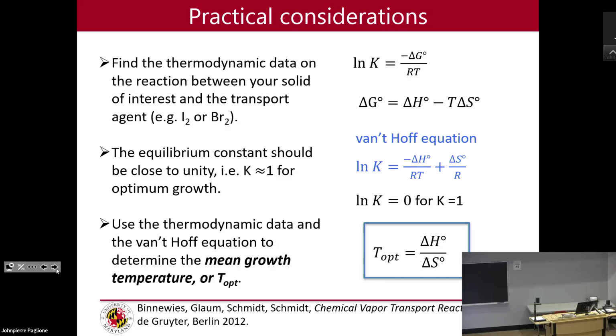Okay, so sometimes we get in the habit of just assuming that everything is going to be endothermic, and we just set up the crystal growth so that the charge is at higher temperature and your crystal growth is going to be at a lower temperature. If it was just physical vapor deposition, great. But that's not the case many times, right? If you're doing chemical vapor transport, you have to actually consider how the chemical equilibrium is going to shift. So that's one of the first things you want to think about. In general, sort of a rule of thumb is you want this equilibrium constant to be equal to unity, or 1, and therefore you want the optimal temperature to be the enthalpy over the entropic term, all right?